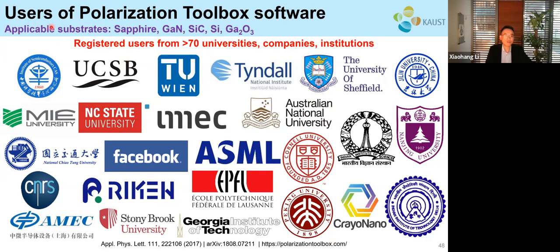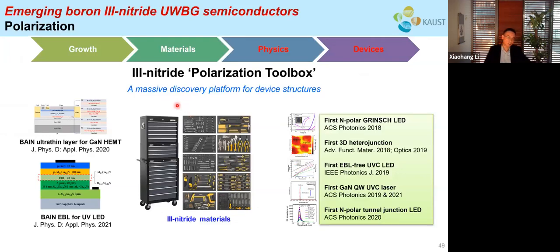The applicable substrates include sapphire, gallium nitride, silicon carbide, silicon and gallium oxide. So covering most of the substrates people use for 3-nitrides. And so far there have been hundreds of registered users from over 70 universities, companies, and institutions using our software. And for us, the polarization toolbox is also a massive discovery platform for device structures. Not only has it contributed to our type 2 heterojunction study on gallium nitride transistors and LEDs, but also it has led to several of our significant studies, including the first nitrogen polar GRINSCH LEDs, the first 3-dimensional heterojunction, and so on.